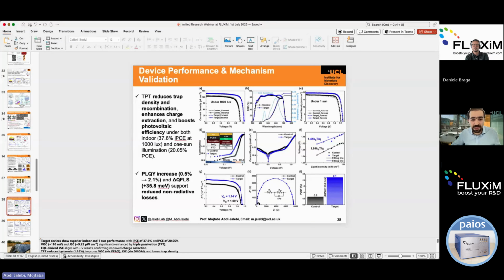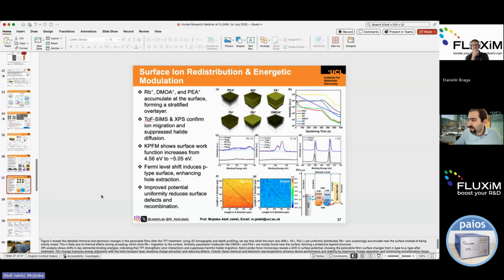It can be applied to other perovskite bandgaps as well, but you need to be careful in tuning the concentration you're using, and in how you're playing with the work function, because another mechanism of enhancement was tuning the work function. As you can see, we show more p-type properties of the top surface of the perovskite using KPFM. That means a better alignment with the HTL as well.